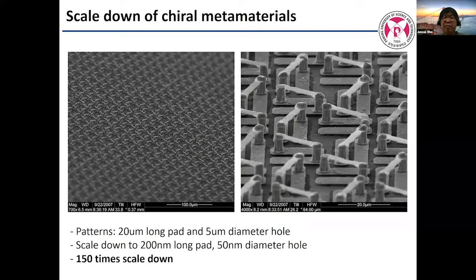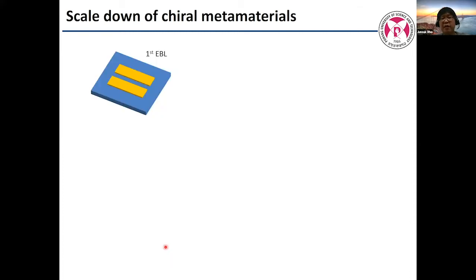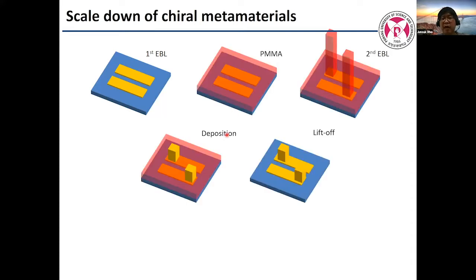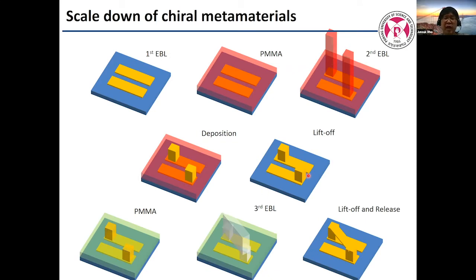So we tried to make the previous micro chiral metamaterial about 150 times smaller. This is the first lithography by e-beam, and then gold deposition and lift off. Then the second one, PMMA, and again making holes here, deposition, lift off. Then the third layer is a little tricky, because if we expose here, normally the beneath of this suspended bridge is also exposed. So we do grayscale lithography, only exposing a certain depth of the photoresist, only a few tens of nanometers on top. And then we do deposition and lift off. That makes this suspended nanoscale 3D chiral structure.